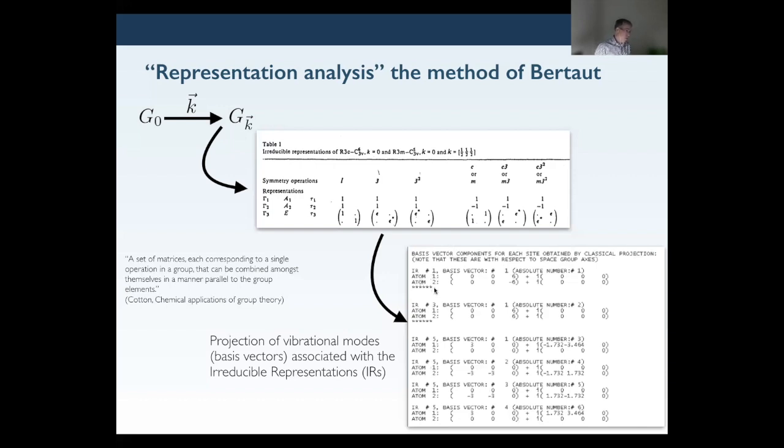We have 2 magnetic atoms, or atoms at 2 symmetry-related positions. Each magnetic moment has 3 degrees of freedom, so with 2 atoms, we're going to have 2 times 3, which is 6 degrees of freedom in our system. Our first one was antiferromagnetic along C. Our next one is ferromagnetic along C, but we still have another 4 degrees of freedom left. And these 4 degrees of freedom have to create all of the other structures that are not in these irreducible representations, because irreducible representations represent orthogonal structures.